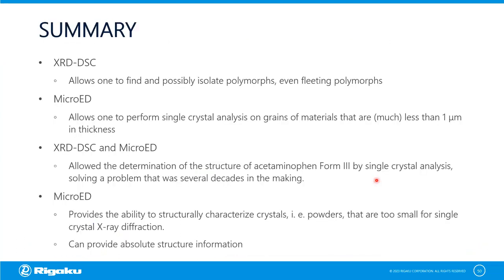So in summary, what we were able to do is use XRD DSC to isolate a particular polymorph, typically a fleeting polymorph, and give us enough information to capture that polymorph in a way that we can use to do more structural studies. We then use micro-ED to perform single crystal analysis on grains, that is isolated powder material, that are much less than a micron in size. And this combined technique allows us to determine the structure of acetaminophen form 3 by single crystal analysis, solving a problem that was several decades in the making.